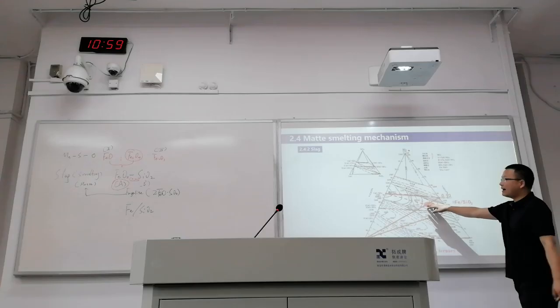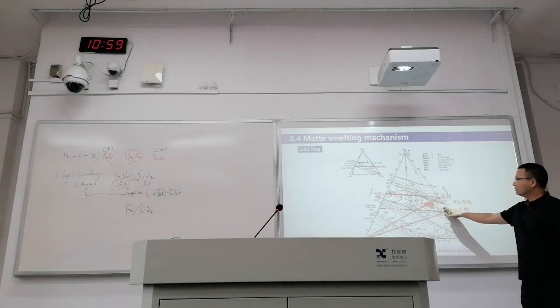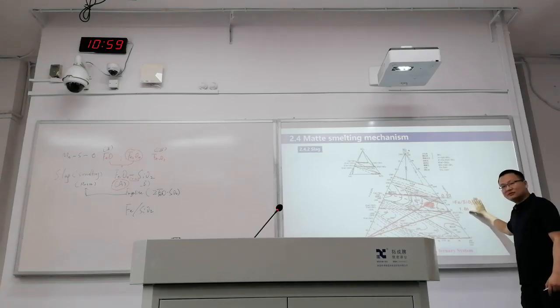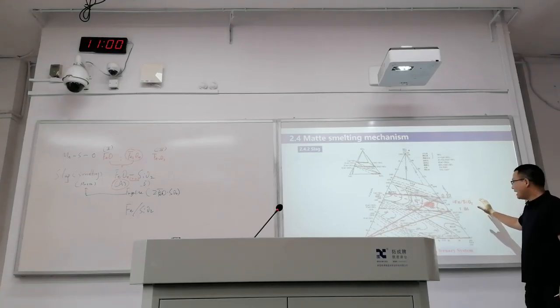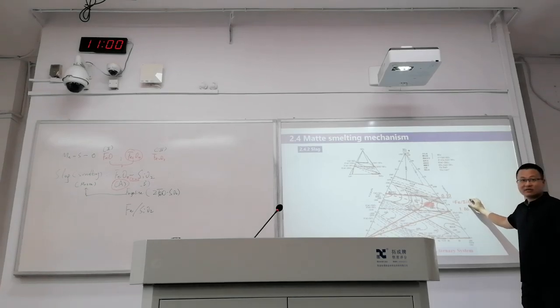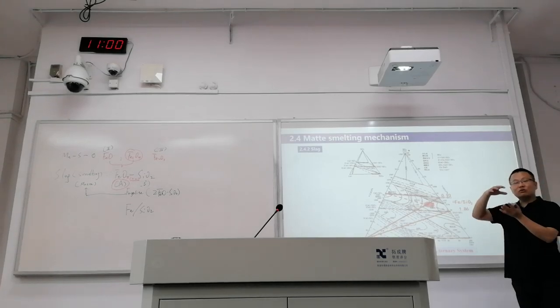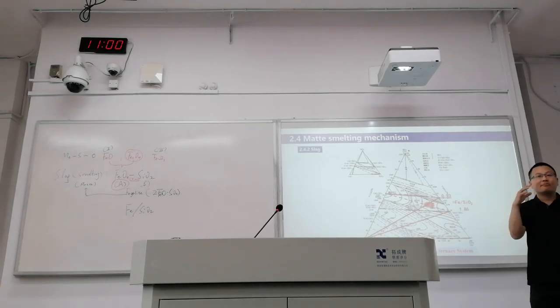And if we are moving back from here to here, and we have made calculations, when we are having a larger iron silicon ratio, we are adding a small amount of silicon oxide, which means the total amount of slag will be smaller.